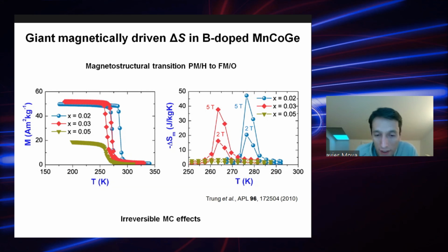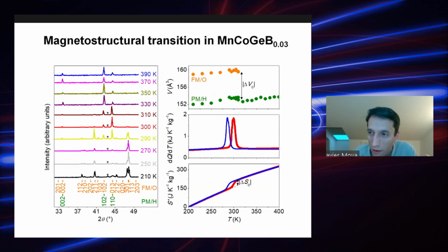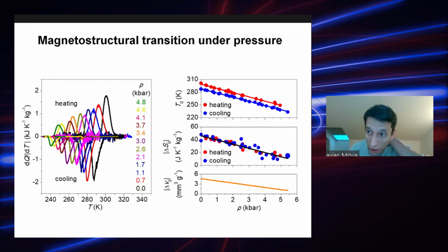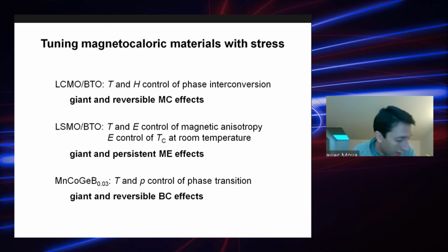So I think there are materials out there that can be quite interesting for barocalorics, even though for magnetocaloric perhaps are not reversible. And with this, I just conclude. So I show you 3 different examples of how you can take traditional magnetocaloric materials and use stress and strain to get new properties out of them. For the case of LCMO/BTO, you can use a strain to get these extrinsic magnetocaloric effects. For the case of LSMO/BTO, you can use these changes in strain to get large magnetoelectric effects. And in the case of the boron-doped manganese cobalt germanium, you can use electrostatic pressure instead of magnetic field in order to get reversible caloric effects. And with that, I thank you for your attention. Thank you very much.